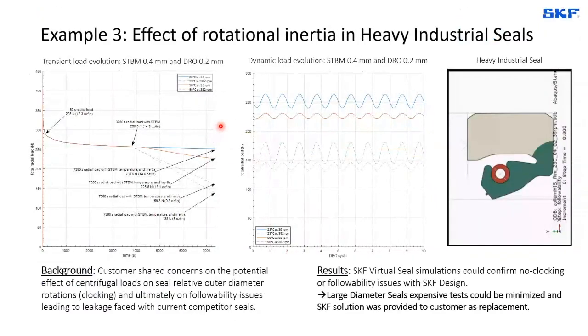Another interesting example is when it comes to an industrial application with a bore rotation in this case, where a customer was facing issues with competitor seals for different reasons. One of them was basically a clear leakage coming from a loss of contact, it seems. And the customer was interested in the effect of rotational inertia onto the actual lip force. And so basically the SKF virtual seal was used to be able to assess, first of all, the relaxation coming over time for this seal, but also, once the centrifugal load was applied, how the force would decrease at the lip due to the bore rotation in this application.